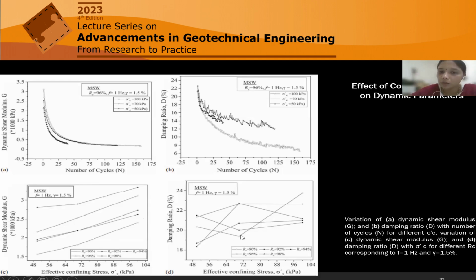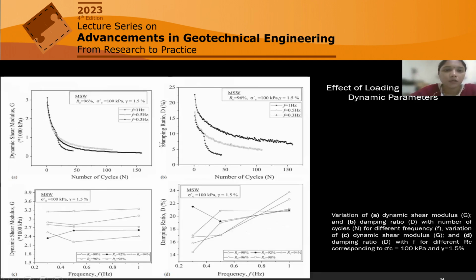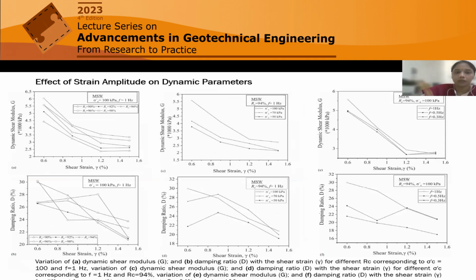But for damping ratio, we are not getting any proper trend, in a few cases increasing, in a few cases decreasing. But if you check the frequency effect, the frequency of loading is not affecting much. We cannot see any significant effect of frequency on G and D, meaning dynamic shear modulus and damping ratio, for this particular MSW fines. And this has been compared with other past researchers also. They also found the effect of frequency is negligible and not significant as compared to confining pressure and relative compaction.